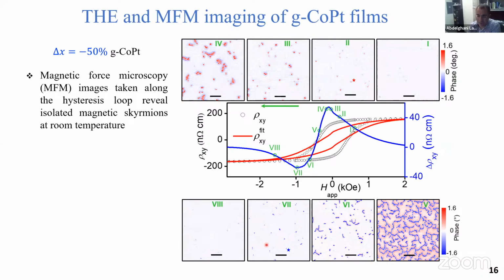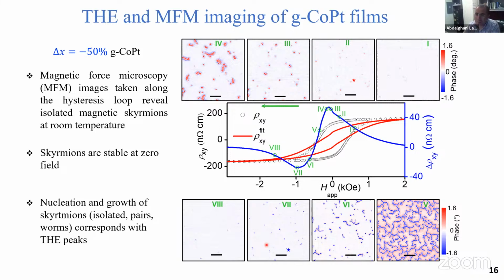In both cases, in particular this domain structure here, usually it is a little bit on the negative side, but you can also stabilize skyrmions at zero magnetic field. So this is very interesting. We found creation of complex spin textures, like worms and pairs, which I will discuss later. This correlates very well with the Hall effect. This is done on the negative gradient sample.